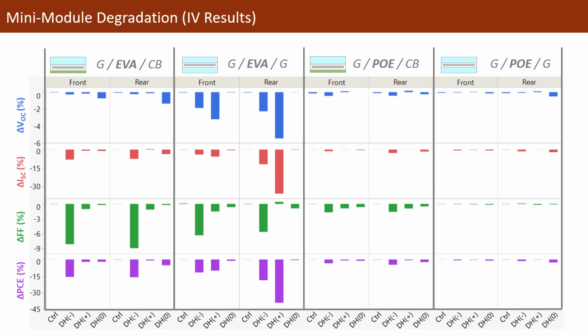the rear side of each mini module, including the 4 different module constructions that we made. Along the bottom of the chart, you'll see the 4 different stress tests listed for the measurements both for the front and the back side, including the control samples, damp heat under negative bias, damp heat under positive bias, and damp heat under zero bias.